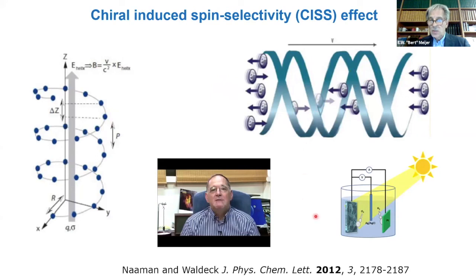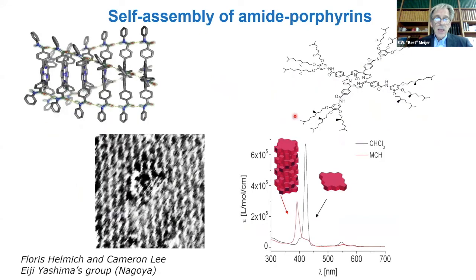And it would be great to use that, for instance, for water splitting. First, it would be great to show that you can do spin-controlled chemistry. We did that with a porphyrin, a zinc porphyrin you see over here with amides, and it has tails to make it soluble, it has stereocenters to make it chiral. We can control the monomer, the polymer.